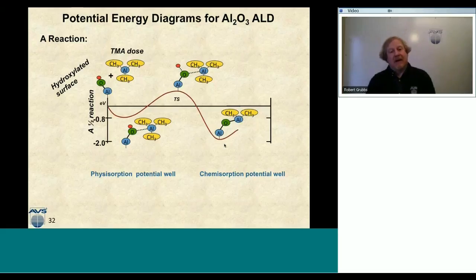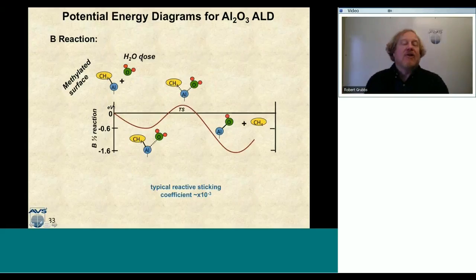Now there's a similar potential energy diagram for the B reaction. Here's my methylated surface. I'm coming down with water. Water falls, gets physisorbed onto the surface and makes this bond here, probably again with the non-bonding electron pairs of the oxygen seeking the nucleus of the aluminum atom. And as that is in equilibrium, I start to march up the transition state, and aluminum would much rather be bound to oxygen than the methyl group. And so then this transition state moiety falls down into the chemisorption well. I make the aluminum-oxygen bond, and then I leave methane into the gas phase.